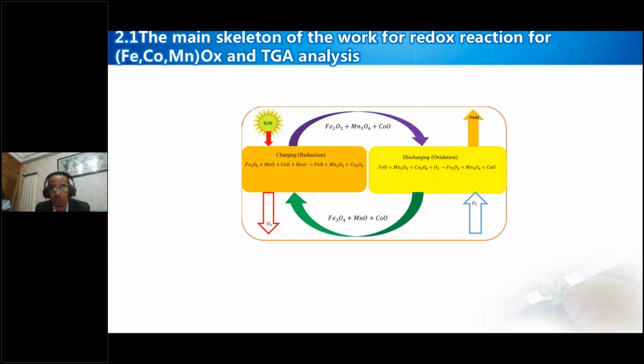We analyzed under thermogravimetric analysis, and after we got a result for this manganese and cobalt oxide, we selected a good proportion for cyclic stability, and then we added iron at last. The main purpose is to find which part of the composition of iron manganese oxide is important, to later develop for energy storage application. So we have done different proportions.